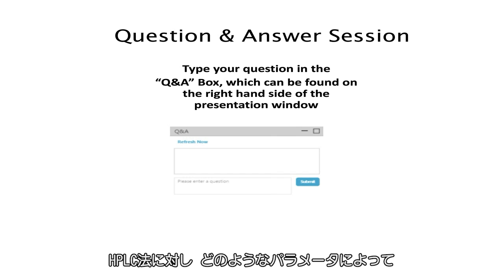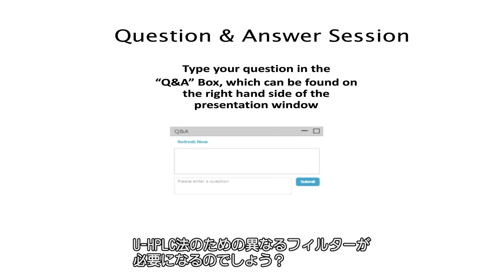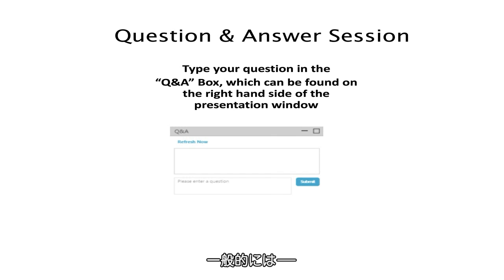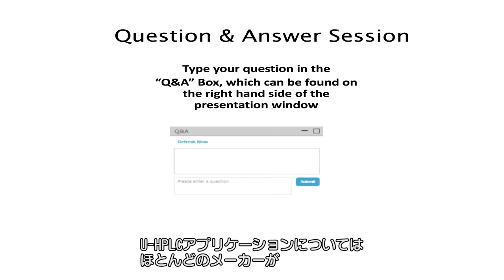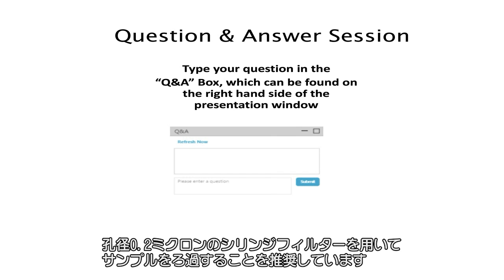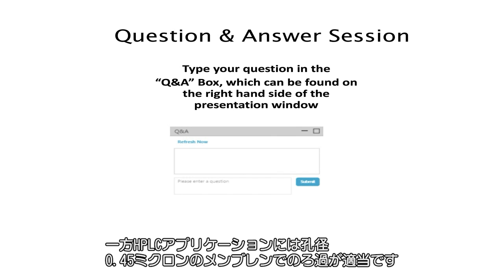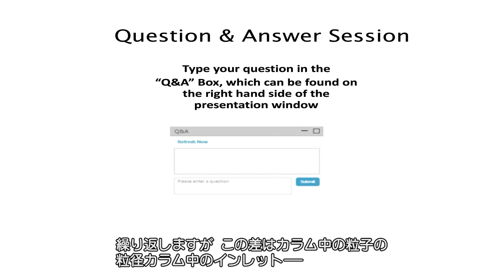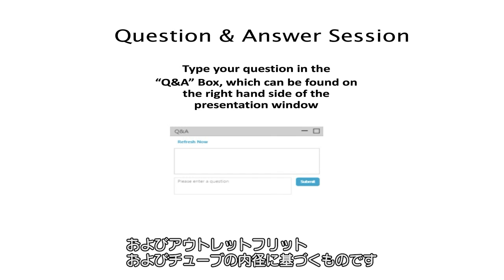Thank you. And what parameters might cause a different filter to be needed for a UHPLC method versus a HPLC method? So typically, for UHPLC applications, most of the manufacturers recommend that filtration using a 0.2 micron syringe filter for sample is what is considered ideal, whereas filtration using a 0.45 micron membrane is suitable or sufficient for HPLC application. And again, this difference is based on the particle size of the particles present in the column, as well as the inlet and outlet frits that are present in these columns, as well as the tubing dimensions.